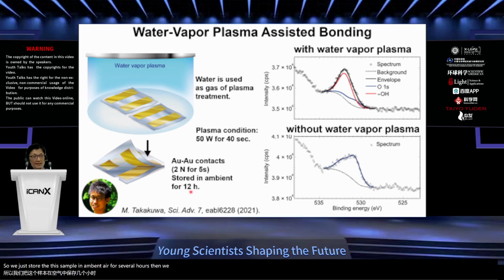Then we can make perfect bonded interfaces of these two gold surfaces. And the important mechanism is the generated OH regions on the gold surfaces after the water vapor plasma treatment.